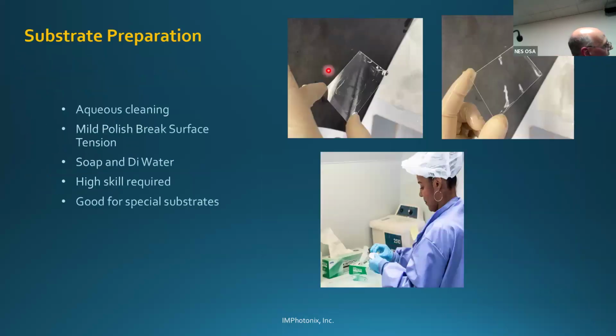Okay, all right, so it's getting late, so I'll just really quickly go through this. If anybody has any questions about substrate preparation, let me know. There are different ways of doing it, but the most important thing is that you want to make sure that the surface has no tension on it. And we do a water break test, because if there's tension on the surface, it would cause issues with streaks in the film after we deposit it. You can see it by running it underwater, and you see where the water is sticking to the substrate. After it's cleaned, it should just run right off.